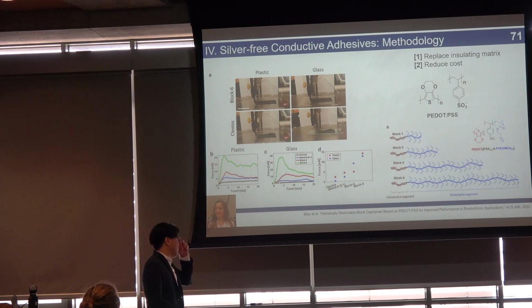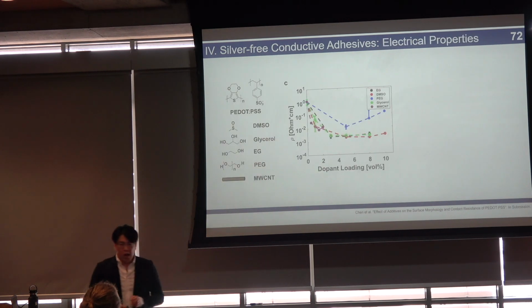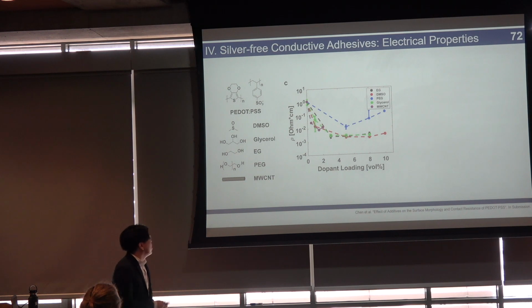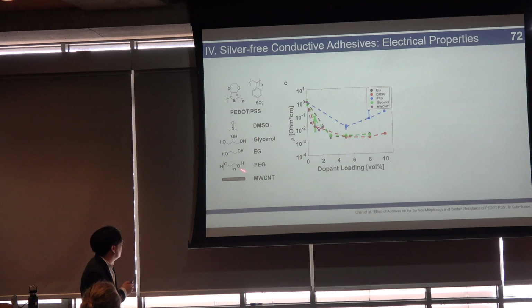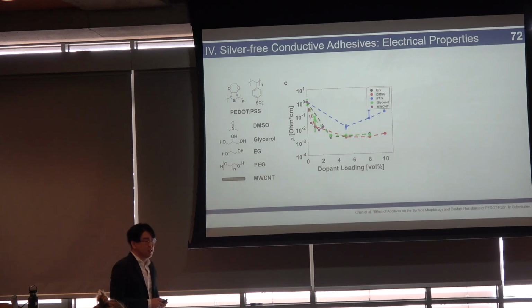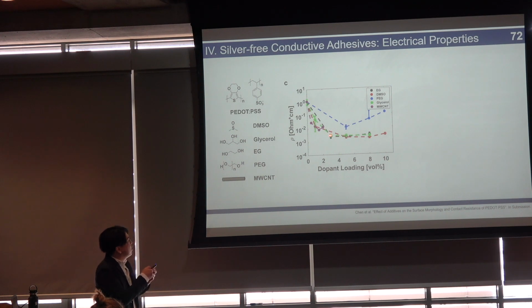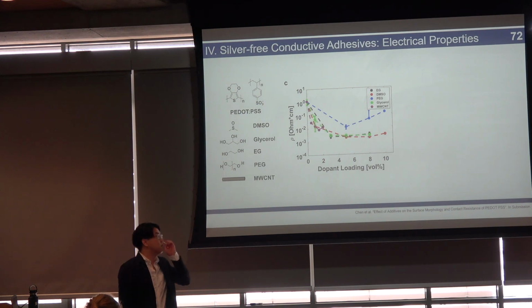So we started looking at PEDOT:PSS, and what we did was we added some stuff to it to try to improve the electronic properties. We added these polar small molecules, DMSO, glycerol, ethylene glycol. We added polyethylene glycol, and we added multi-walled carbon nanotubes. And over here is the bulk resistivity of our material. We actually see that the polar small molecules outperform the carbon nanotubes. So this is actually pretty cool. This means that we might not even have to add electronic filler.